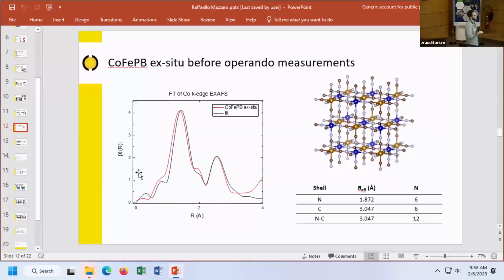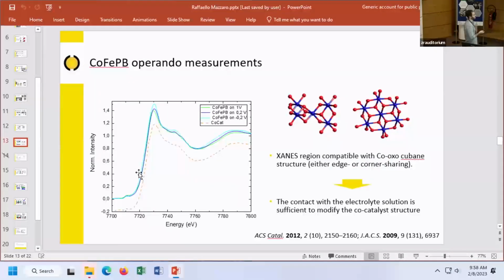We just tried to do some extra analysis on the sample X to be sure that we started actually from the structure we were interested in. So the cobalt iron Prussian blue, that is, we have cobalt and iron sites at the corner and bridged by cyanide ligands. And this is actually fitting pretty well, not perfectly, but pretty well.